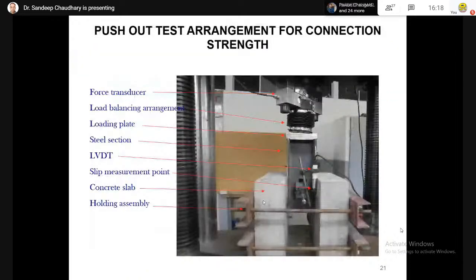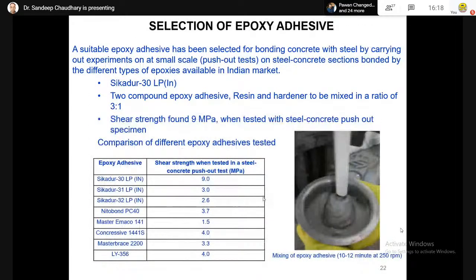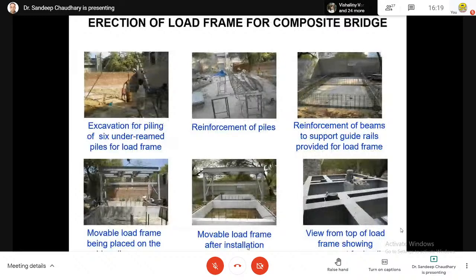Now, to check the epoxy, what is very important is that there is no standard epoxy available in the market for the composite action of structural steel and concrete slab. So a lot of epoxies were tried, different epoxies from different manufacturers, and even from the same manufacturer, different varieties of epoxy. Like you can see, the shear strength was checked for different types of epoxies. Finally, we could freeze on one epoxy, Sikadur 30, which had a strength of 9 MPa. So we worked on that epoxy later on. Of course, here the mixing process is also shown. You have to mix epoxy for 10 to 12 minutes at 250 RPM.